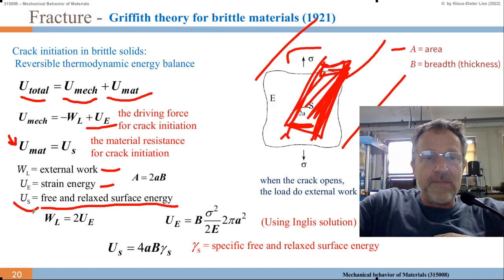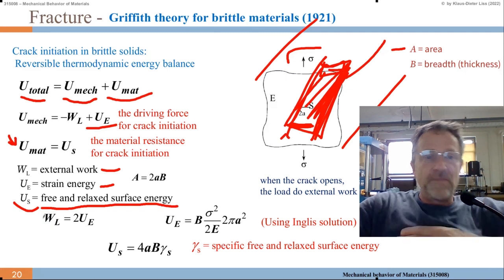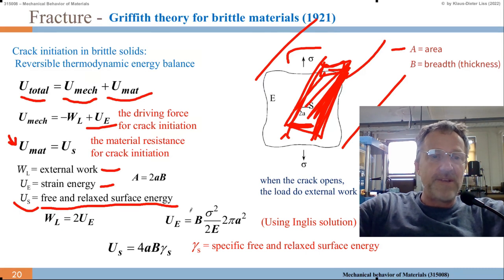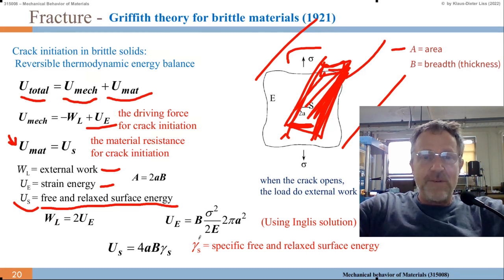So WL becomes 2 times UE, the strain energy, and UE then with the Inglis solution becomes B times sigma squared over 2E, times 2 pi A squared, and US is 4 times A B gamma S.